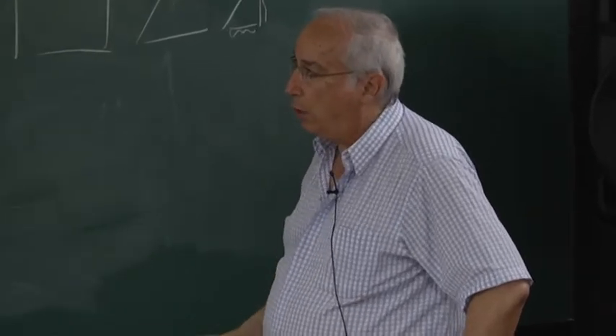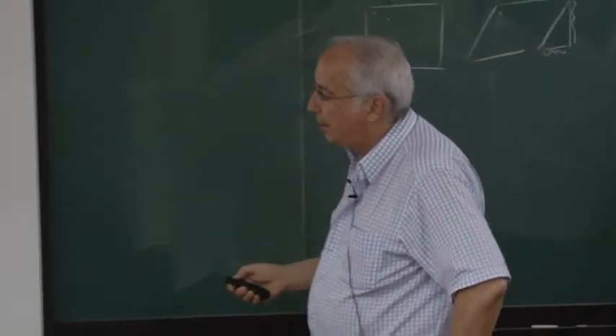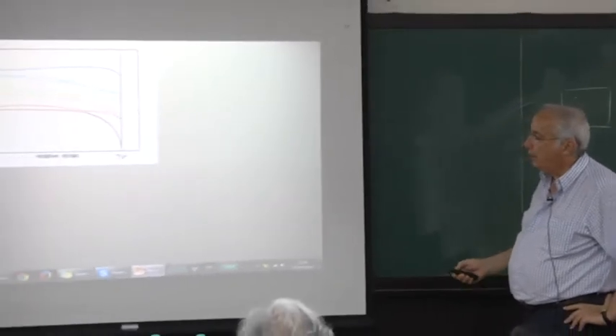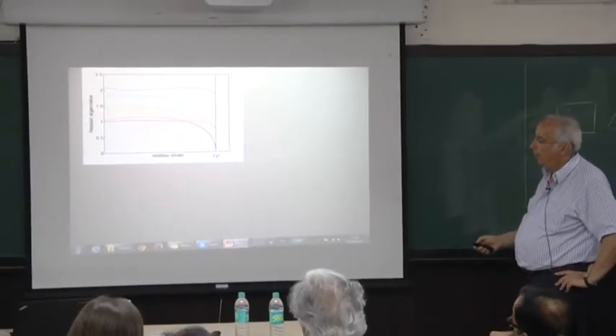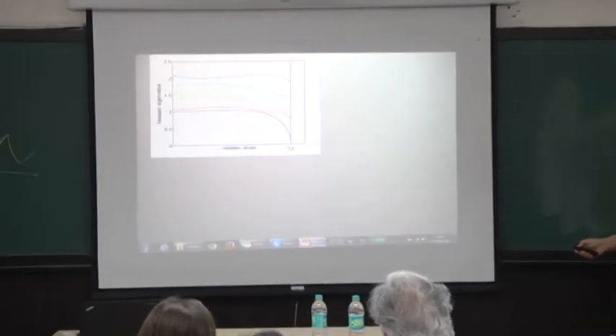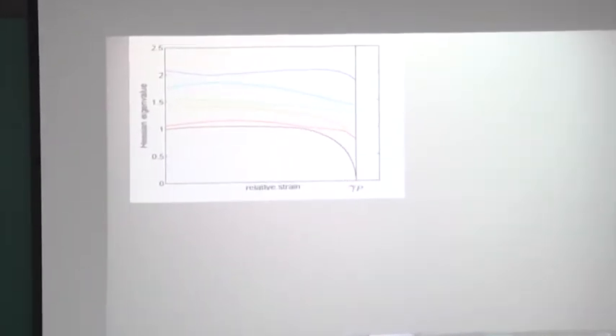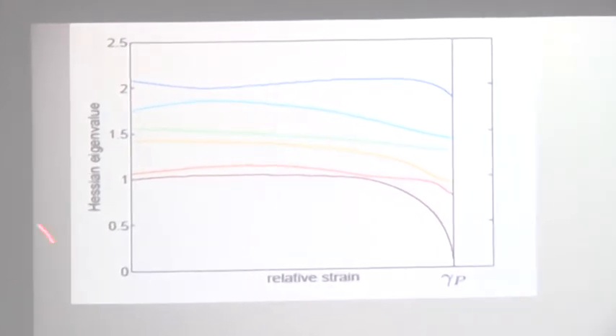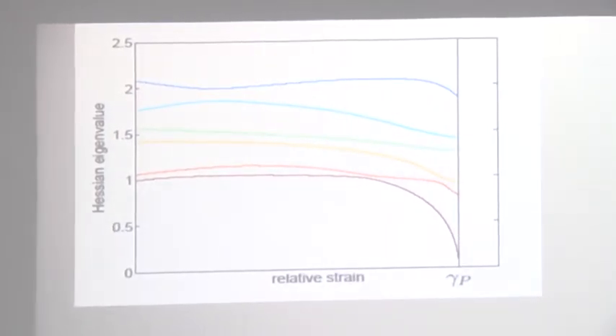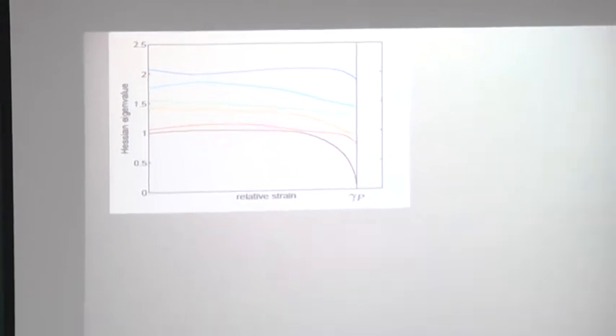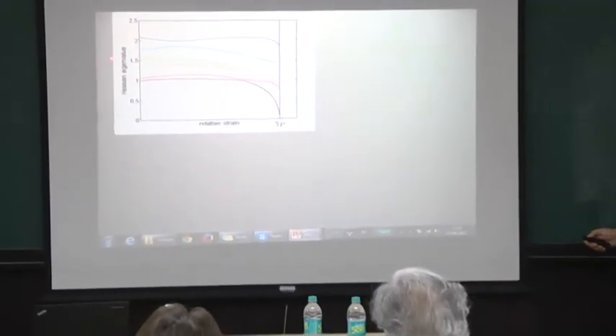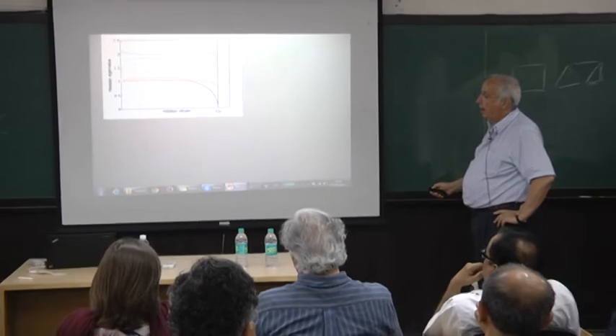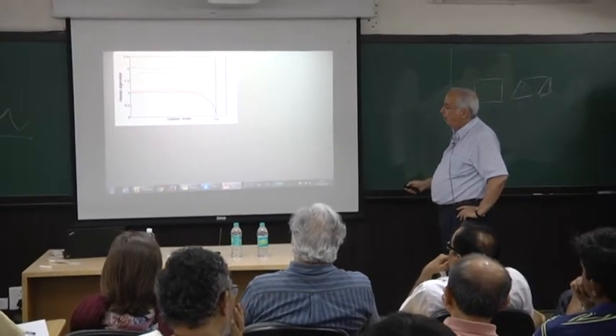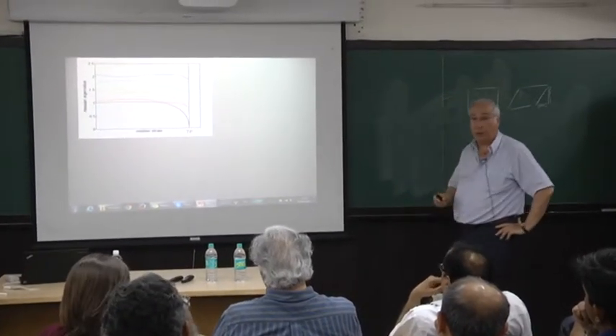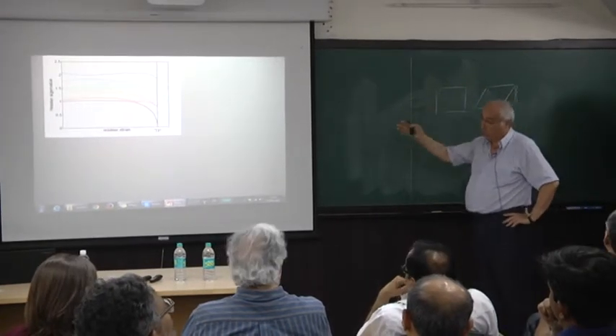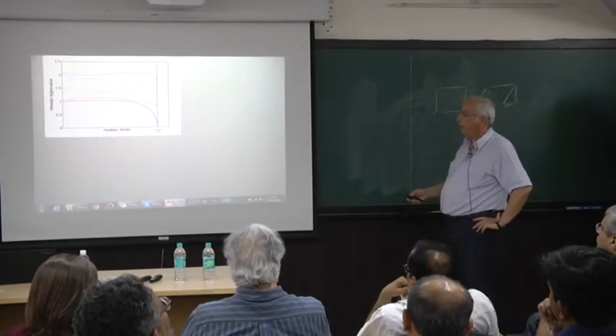So how does it look? Well, here is an example for a system on the machine. These are the leading eigenvalues of the Hessian matrix as a function of the relative strain gamma. And as you see, there are some eigenvalues that care very little. You change gamma, well, they do have some dependence, but nothing really dramatic. But here is one that cares a lot. This is an eigenvalue that starts at a finite value and is a function of gamma, and at the value gamma p, bingo, it goes to zero, and a new phenomenon is occurring.